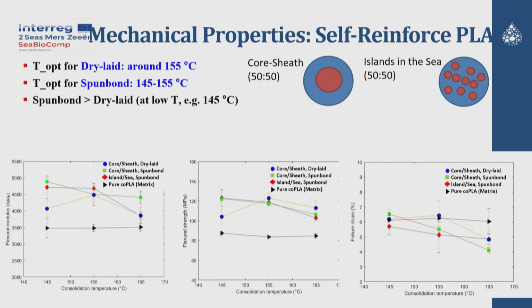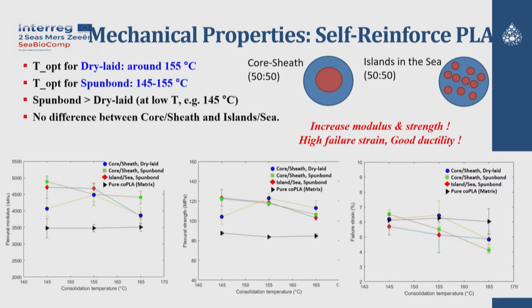In terms of comparing the two different nonwoven technologies, we found that the spun bond is a little bit better because the process window was a little bit wider. And we observed no difference between core sheath and island in the sea. Anyhow, we could increase modulus and strength without compromising failure strain and ductility. So we could obtain a stiff, strong material, and at the same time, it is also ductile.